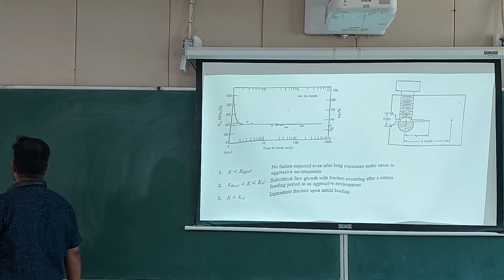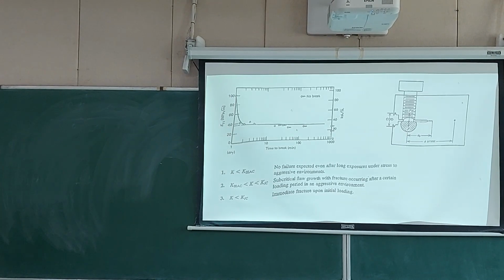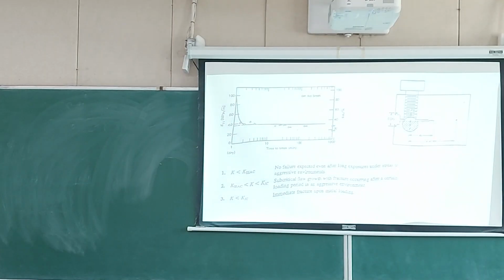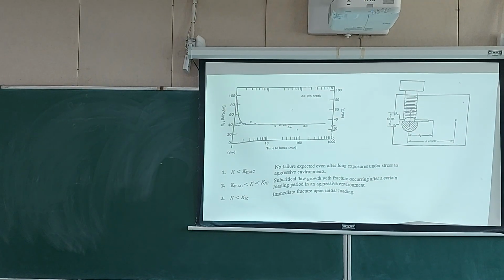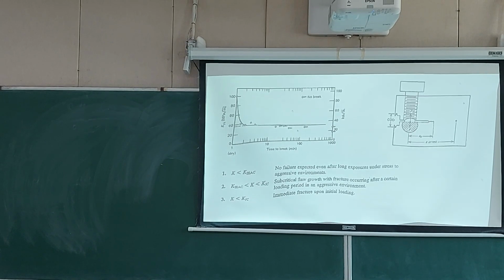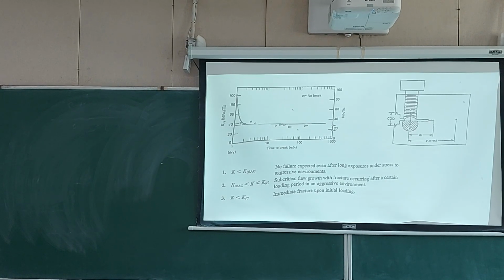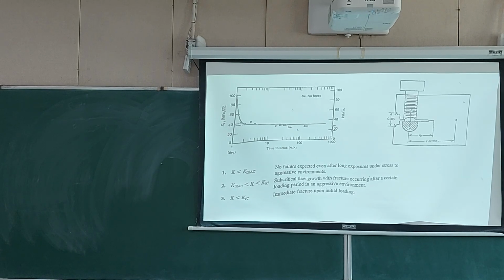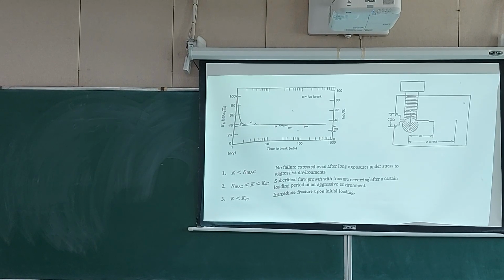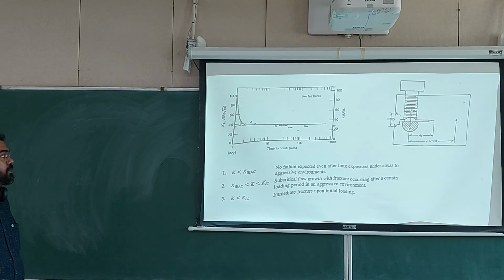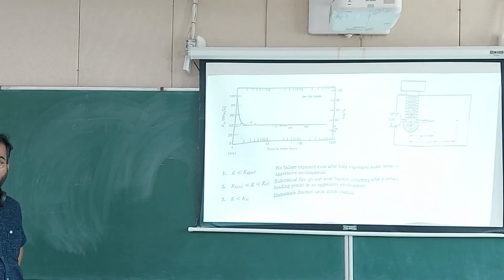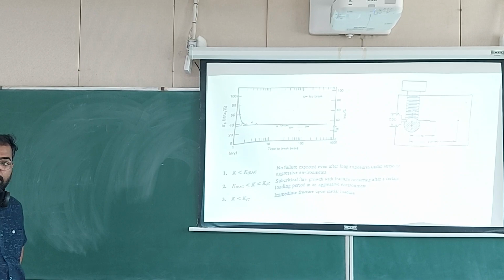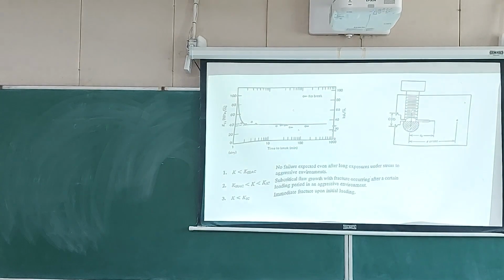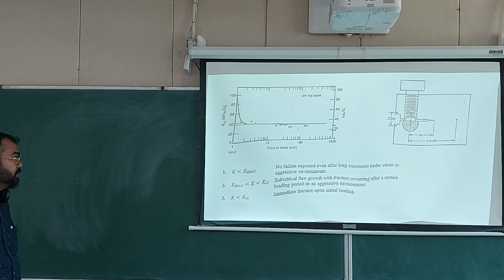In the last class, when we were discussing the effect of corrosive media on fracture toughness, the plot you see on the left hand side comes from multi-specimen testing. So you load a lot of specimens, and this is a normal fracture toughness test. You take your specimen, put it in corrosive media, and let it be there as long as it breaks. Catastrophic failure happens, and you plot that.